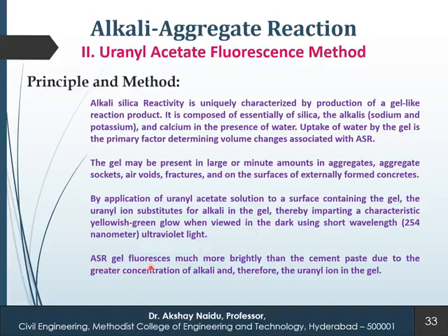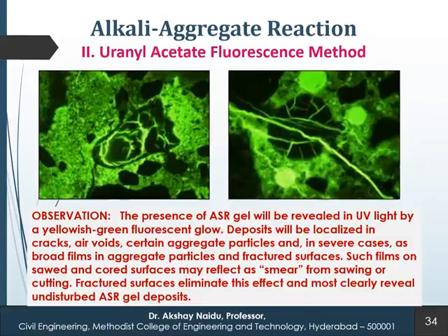So ASR gel fluoresces much more brightly than the cement paste due to the greater concentration of alkali, and therefore of uranyl ion, on the gel. So there's the picture. At the microscopic level, under the petrographic microscope, when uranyl acetate solution is applied, we can see this greenish glow, which is an indicator of alkali aggregate reaction, particularly alkali silica reaction.